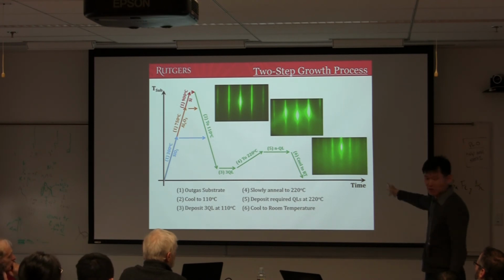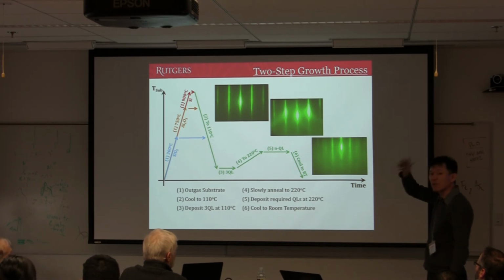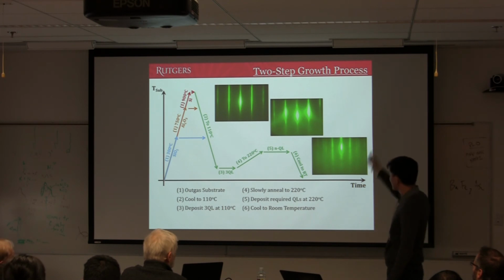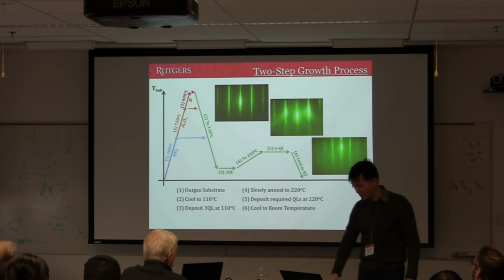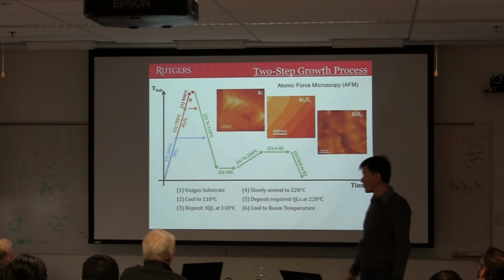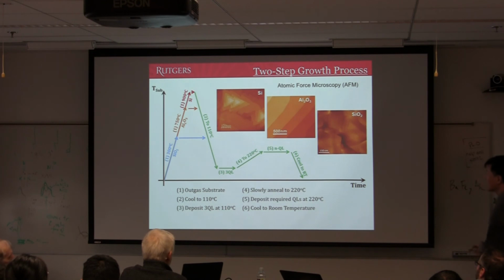You can have at best just polycrystalline, just rings, random structure at best. You never have this nice, reasonably streaky pattern. So this implies bismuth selenide can be grown on almost anything. But depending on the substrate, the quality changes a lot.